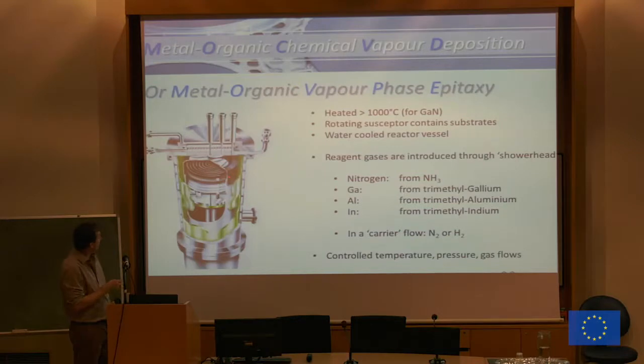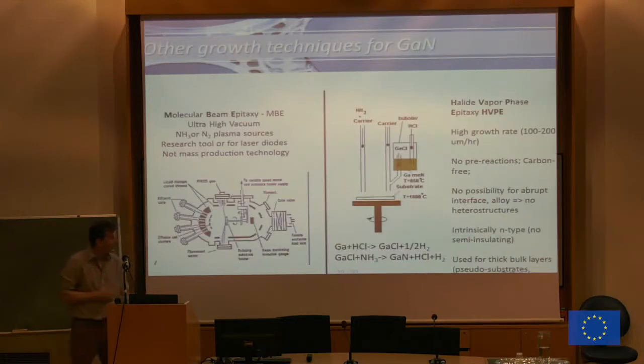So typically a reactor looks like this. We have a susceptor where we put substrates on top. We will heat this up to relatively high temperatures for gallium nitride. Some will say it's low temperatures if you do aluminum nitride, but still we are above 1000 degrees. And then we insert these reagent gases, so the metal organics, and for nitrogen we use typically ammonia as a source. We emit that here through this shower head so that in the area above the substrate we can have some reactions.